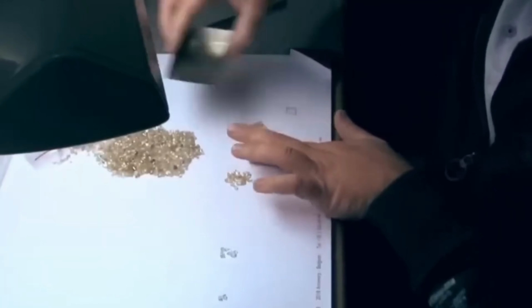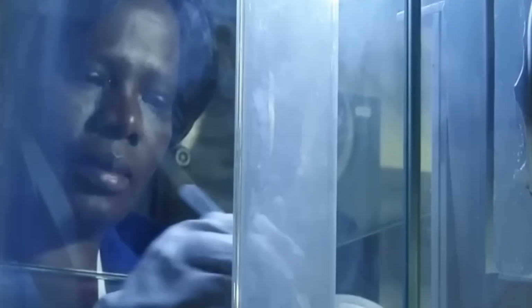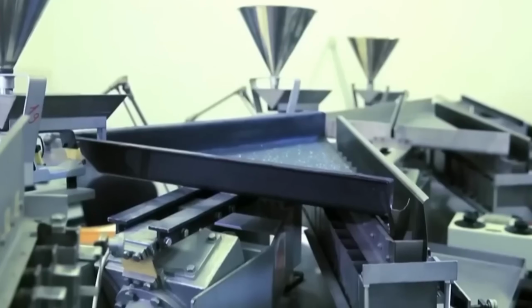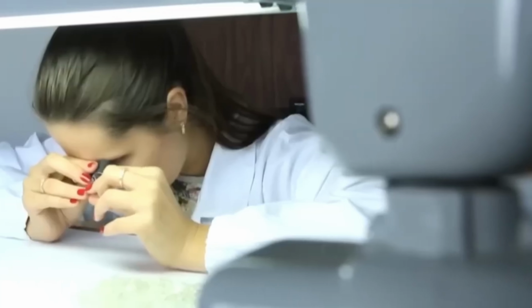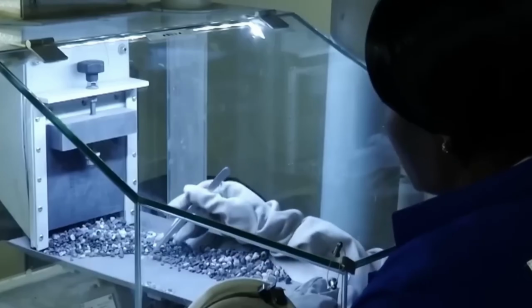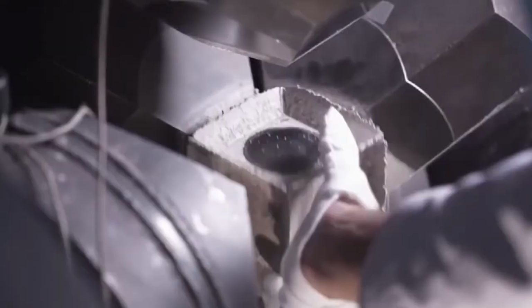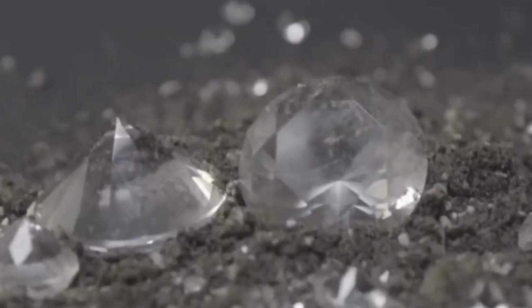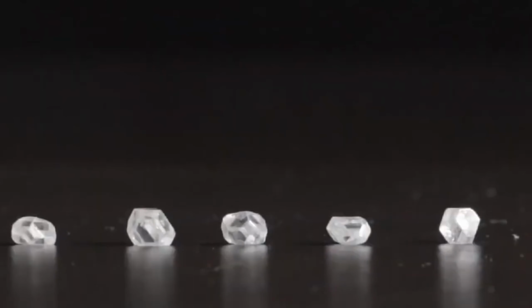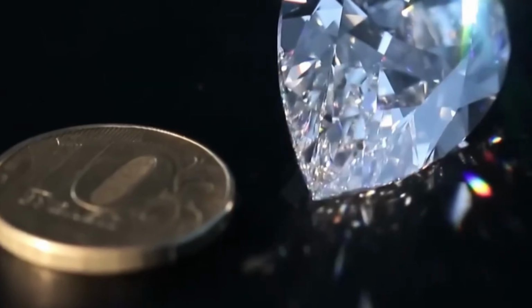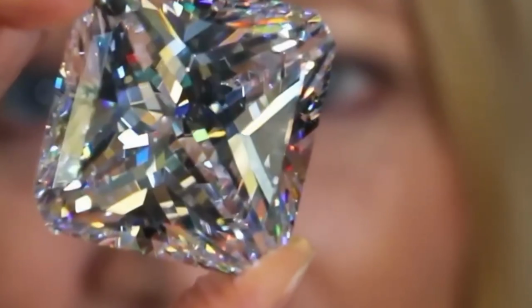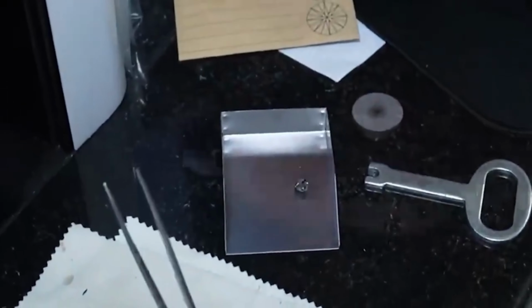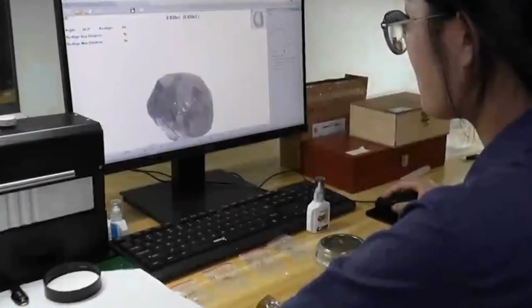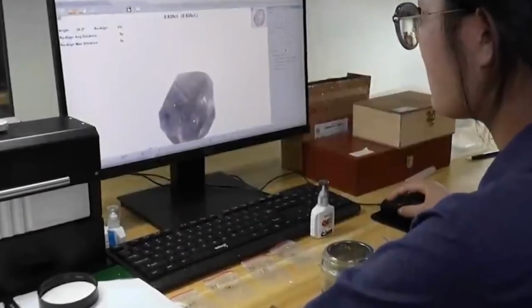diamond is removed. Once the rough diamond exits the press or chamber, the next step is annealing, a controlled heating process that relieves internal stress created during growth. Annealing stabilizes the crystal lattice, improves clarity, and corrects any color inconsistencies caused by metallic inclusions in HPHT growth or structural strain in CVD growth. Diamonds are loaded into high-temperature furnaces and heated to several hundred degrees or sometimes over 1,000 degrees Celsius, depending on the type of correction needed. The diamonds are then cooled slowly, allowing internal tension to relax. This step is critically important because diamonds that retain internal stress can crack when cut or polished.